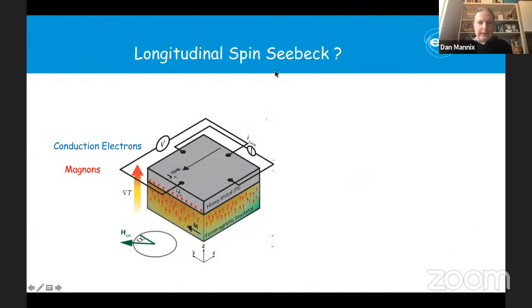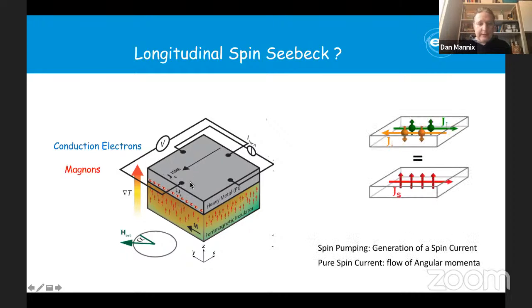So what are these materials about and what do they look like? Well, actually what we have here is, in our particular case, these are ferrimagnetic materials. These are insulating materials, they're oxides. And if you place them in a thermal gradient, you can create a heat source or heat current inside the material. On top of the material is grown a heavy metal, usually platinum. So you have this interface between insulating magnetic state and a heavy metal. And what will happen is that the magnons become excited, and at the interface here, you will set up a spin current going inside the conduction electron. So the interaction between the magnons and the conduction electrons of the metal can give rise to this spin current. And that is basically described as a flow of angular momentum inside the metal. Now that spin current can then be transformed, because platinum is a large spin orbit coupling material. You can transform that spin current into a charge current. And that is then measured as a measurable electricity, transforming the heat into usable electricity. It's a thermoelectric effect.